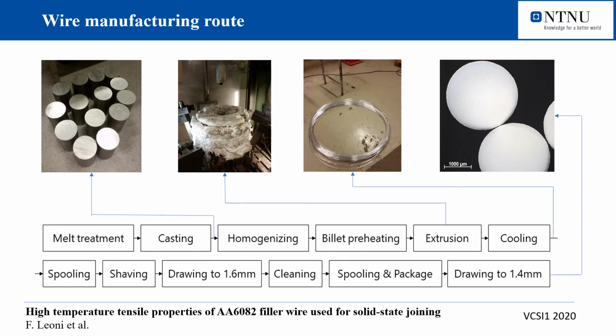The homogenizing of the 95 mm diameter direct cast extrusion billet was carried out at a heating rate of 200 degrees Celsius per hour. The extrusion billet was then held at 540 degrees for 2 hours and 15 minutes and subsequently cooled down to room temperature at a cooling rate of 300 degrees per hour. Prior to extrusion, the billets were preheated at a heating rate of 100 degrees Celsius per minute up to 500 degrees Celsius. The preheated billets were then hot extruded to blank wire of a target diameter of 2.7 mm at a ram speed of 0.6 mm per second.